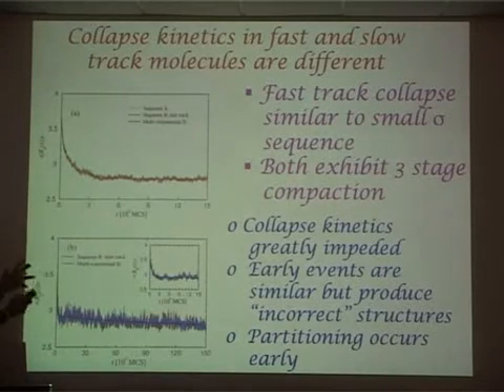The sequence A that I talked about doesn't get trapped in this competing basin of attraction, and therefore all the molecules there, in fact, reach the native state quite rapidly. What is being plotted here is the radius of gyration as a function of time. These are all Monte Carlo. There are three curves in here. One of them is just a multi-exponential fit, and this shows you that radius of gyration compaction takes place in stages. There's a green curve and a red curve that you cannot possibly see from there.